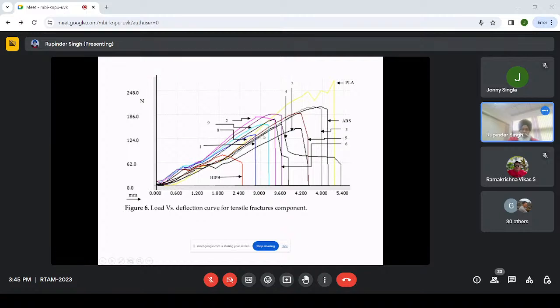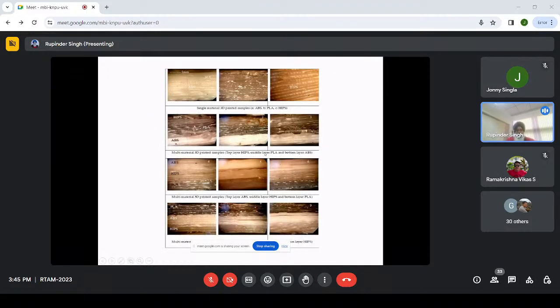area under the curves. Now, if I see the morphology of this, we captured it at 30x magnification using a simple optical microscope, right? If you see for a single material at 30x ABS, there is a layer by layer formation. Here again for the PLA, layer by layer formation, no side flow of material. For the HIPS also, there is an effect of raster, and you can see there is a continuous flow of material layer by layer.